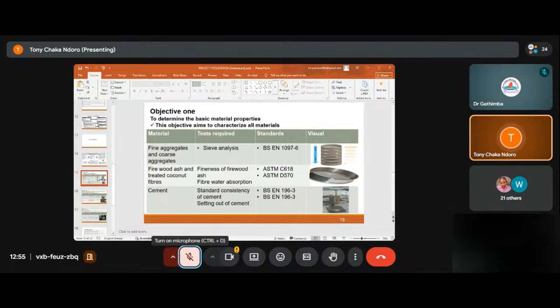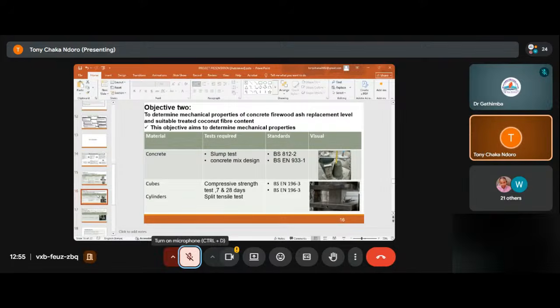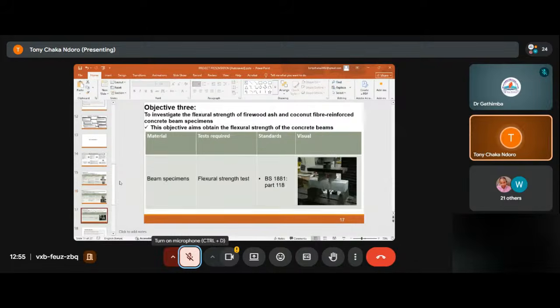This is the objectives: fine aggregates and coarse aggregates sieve analysis, firewood ash and treated coconut fiber fineness, that for the firewood ash, the ones that will pass through the 75 micrometer sieve, coconut fibers water absorption tests, for workability, cement consistency and setting time, concrete slump test, and concrete mix design for the cubes, the compressive strength, and for the cylinders, the split tensile test, beam specimen, flexural strength test.